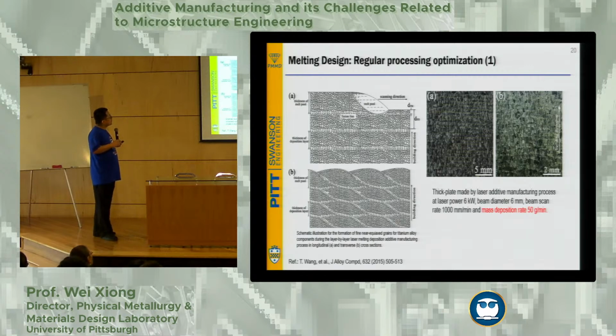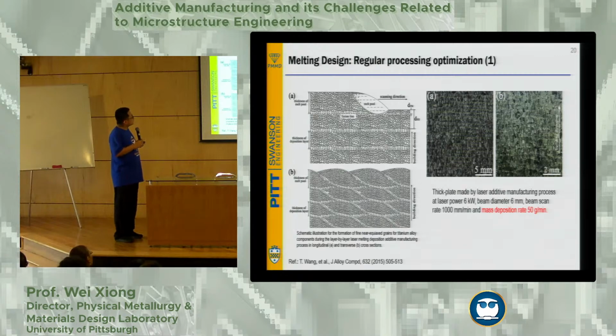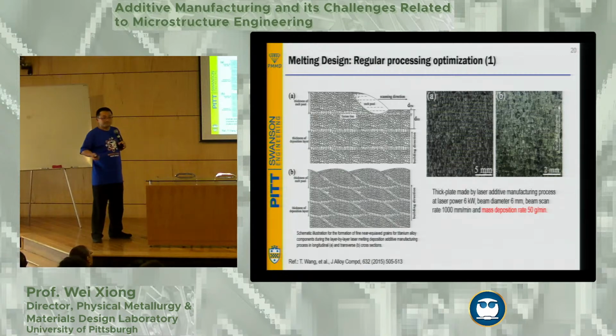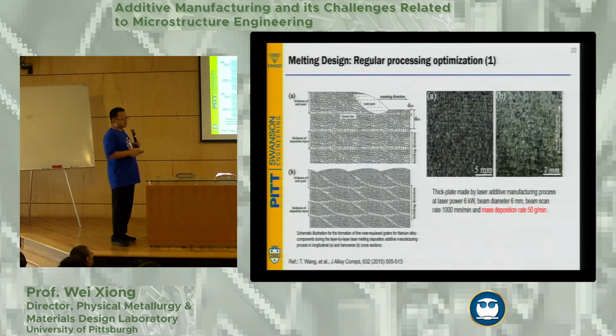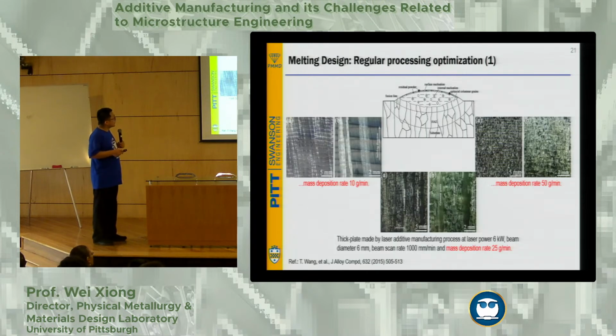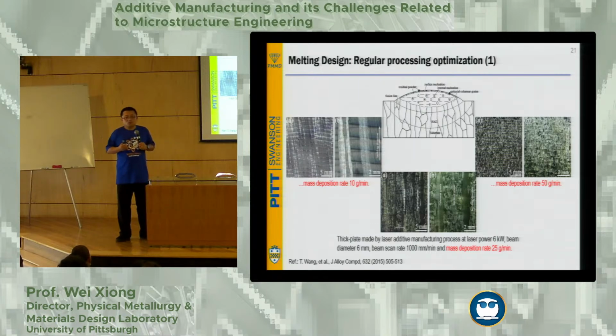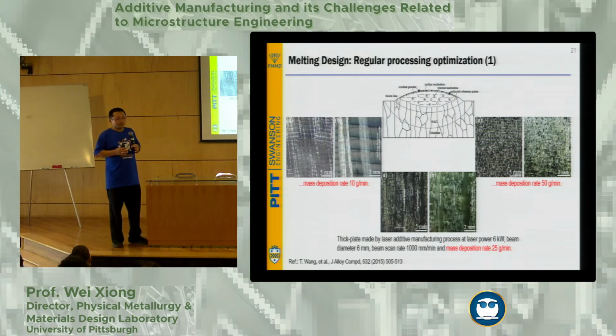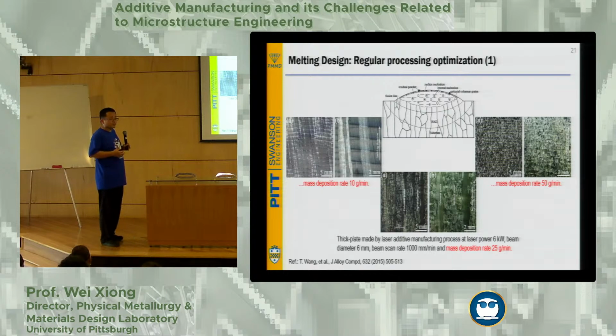So you can actually change the thickness of the deposition layer in order to change the structure with the grains, okay? And then through this, you can introduce layer by layer structure, all right? So this is exactly the concept with the heterogeneous grain structure in the material. And through this, you can actually control the deposition rate, because the deposition rate, if it's high, then it does not allow enough time to have the growth happen. So it's always limited with a nucleation and a very short time with growth. Therefore, you can refine the structure. Okay, that's a basic concept.